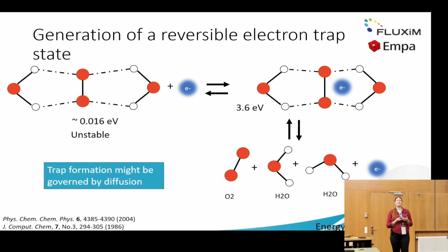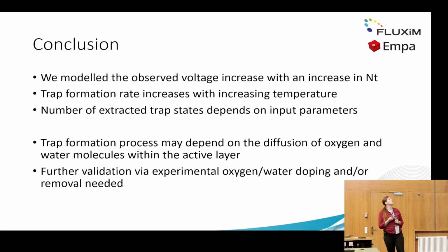dissociate quite fast. So in order to actually get a trap, we need to start from the components, basically meaning that we have a 4-body reaction to form a trap. And the chances of that happening at the same time is not very high, which increases the time of trap formation. This theory has to be tested thoroughly, and we started with kinetic Monte Carlo, but we haven't yet got conclusive results, and I'm running out of time, so I have to come to the conclusion.